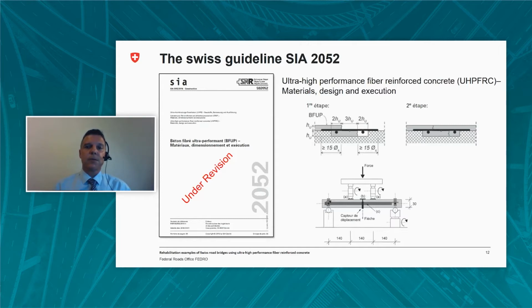A very useful piece of information is the criterion for the sealing properties of the ultra-high performance fiber-reinforced concrete. Based on experimental investigation, it was found that as long as the tension strain in this material remains in the serviceability limit state lower than 0.1%, 1 to 1,000, the sealing properties are maintained. This is of extreme importance since it allows, when designed so, to avoid using complementary layers of traditional sealing for the decks of the bridges and thus avoiding unnecessary costs and delays during an intervention.